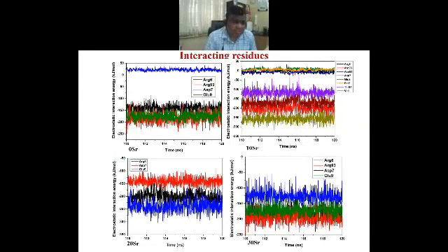And this is how the electrostatic interaction energy for the different protein residues evolves in the particular case of different doped hydroxyapatite. And you can see that for several protein residues, the electrostatic interaction energy is almost 0 kilojoule per mole. That is for at least 3 residues. For most of the other residues, it is more negative.